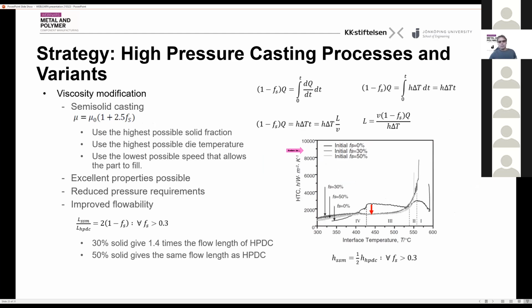Now, there are also some other bits and pieces here. I just wanted to show you this here, which is the fill length, and that means how far you can fill. If we know that we can change turbulence, and we look at the fill speed, knowing that when you have at least 30% solid phase, your heat transfer coefficient, which is H here, is about half of that for conventional casting. And that means that if you lie in the range between 30 and 50%, you get better fluidity as well. So that is also another argument for working with viscosity modification as a means of making high integrity castings. So we can take the next.